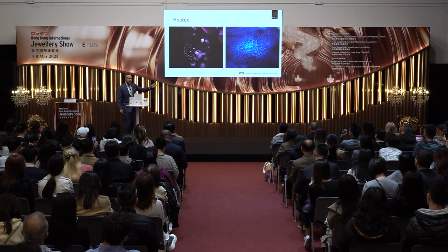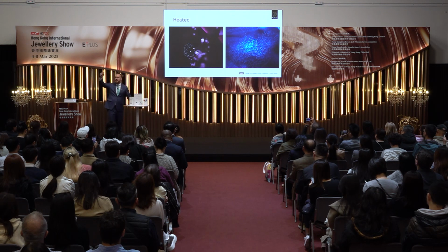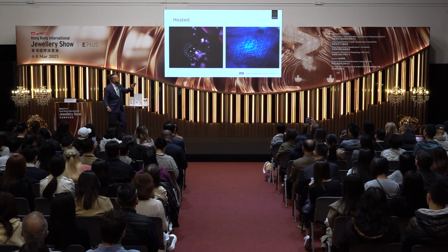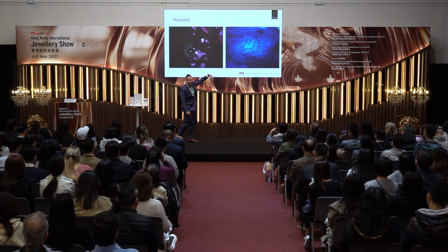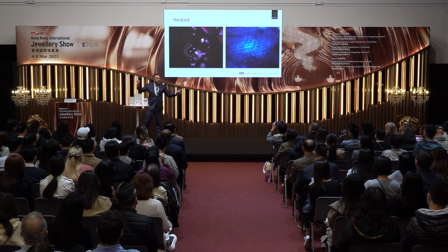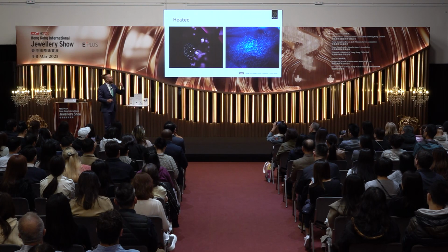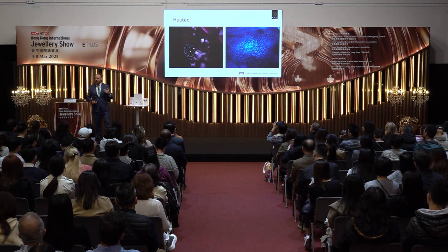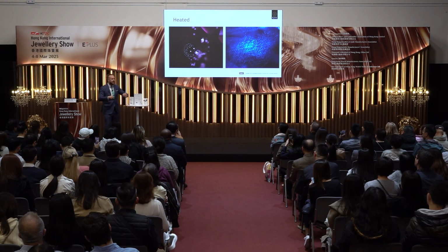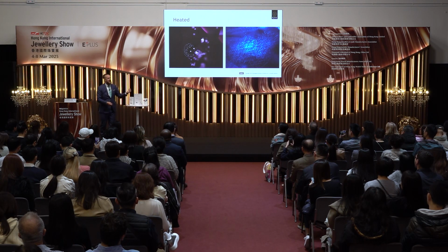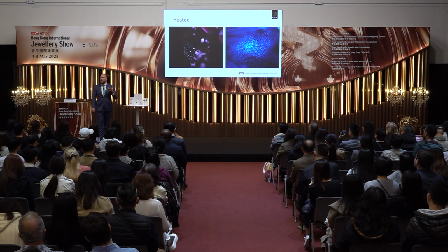The one on the right, if you squint your eyes a little bit, you can see that there's still those resemblance of needles in there. We can still see those patterns like this and like this and like this in there. But those long needles that used to be beautiful strands of what we call silk are now completely broken up. They are what we call peppered. So they're completely broken up in these little pieces, completely degraded. Very classic sign of a ruby or a sapphire that has been heat treated at high temperatures.